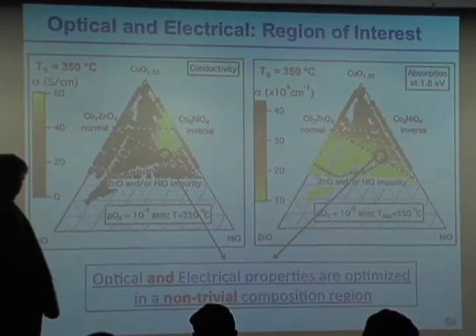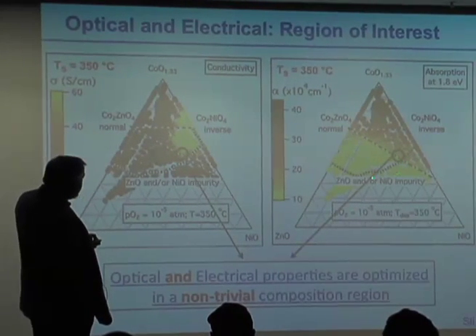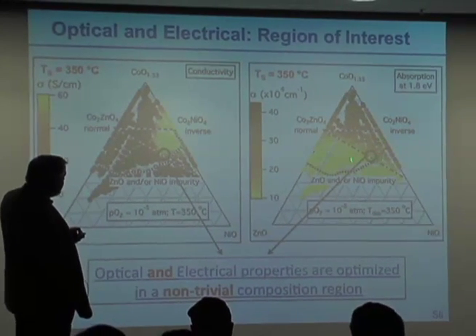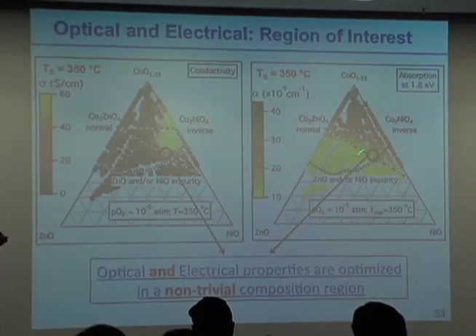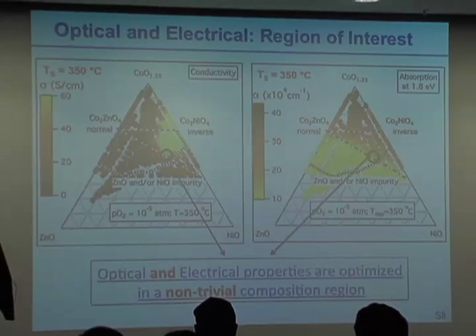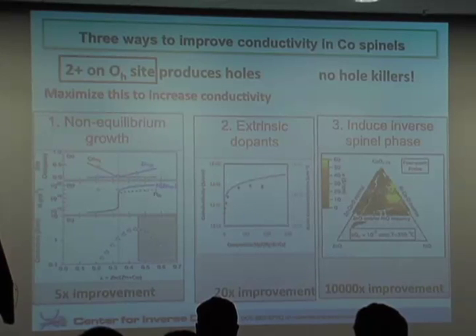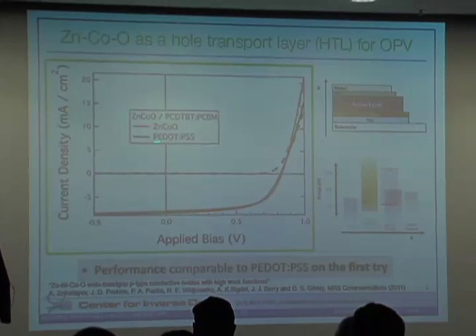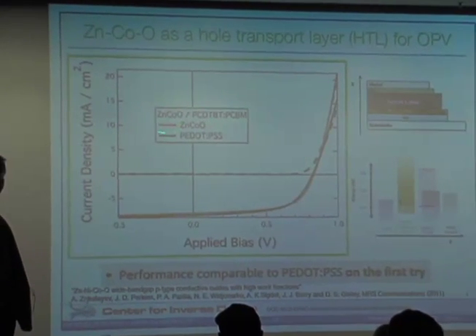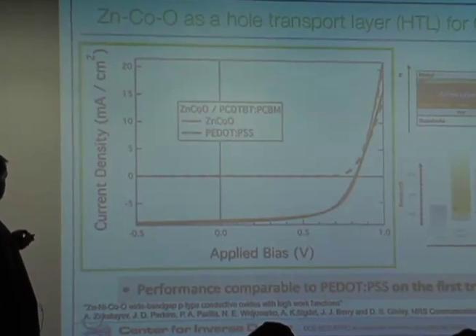Now, one of the issues we have here is this system's still not transparent enough. The band gap's about 1.8 eV. So that's not a very good window for visible photons. But in fact, it turns out that this system can be a very good hole transport layer.